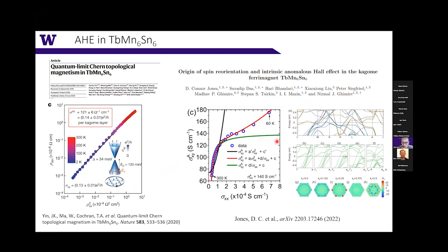They have to include an additional term, which is a spin fluctuation term. With that term, they can fit the whole anomalous Hall conductivity versus conductivity very well. They found an intrinsic anomalous Hall conductivity around 140, not very far from the original number. But they also did band structure calculations and realized that there's a lot of Berry curvature source everywhere in the band structure, so it's not particularly limited to that gapped Dirac fermion.